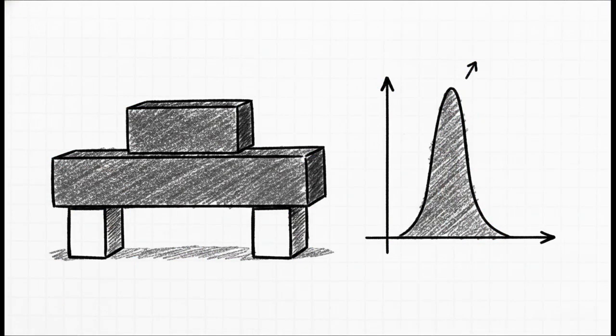And the payoff for using this specific sintering process? It's exactly what your structural engineers are begging for. GPS allows us to achieve incredibly high density and outstanding mechanical properties. We aren't just throwing around buzzwords here. This is validated by rigorous flexural strength data and a very high Weibull modulus. That means its failure rate is highly predictable and incredibly reliable.